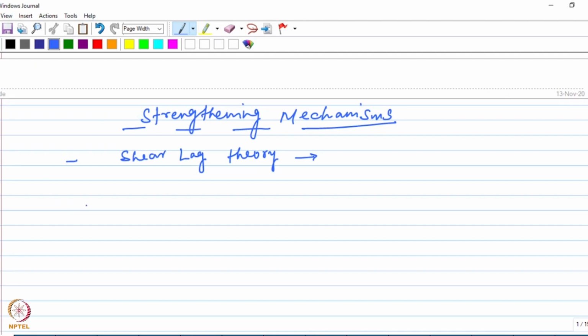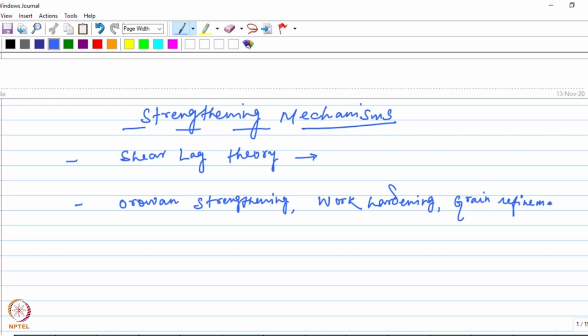And then we talked about the dislocation mechanisms such as Orowan strengthening, work hardening, grain refinement strengthening, and strengthening due to mismatch in the thermal expansion coefficient. Right, so all these mechanisms will ensure that the strength of a composite is higher compared to the unreinforced matrix.